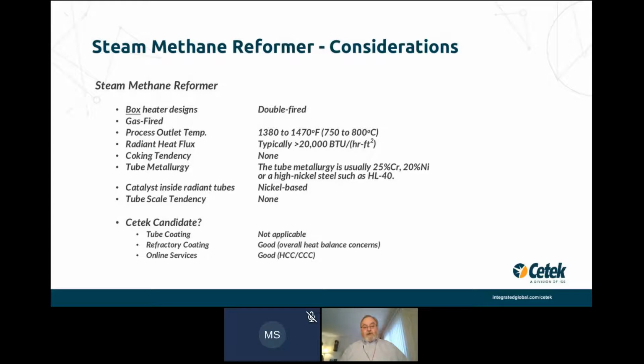And I apologize it's in BTUs per hour because I'm sitting here in the United States, and you know what the Americans are like for changing over to the metric system. There's no coking tendency inside the tubes. The tube metallurgy is a nickel chrome alloy of some sort, and the catalyst is actually inside the tubes, and it's a nickel-based catalyst. Because the tubes are a nickel chrome alloy, there's little tendency for scale formation. They do oxidize, but they form a very thin oxide layer, and typically once that oxide layer is formed, there's very little further oxidation taking place.